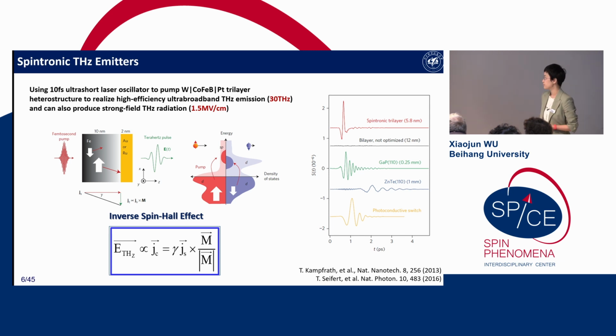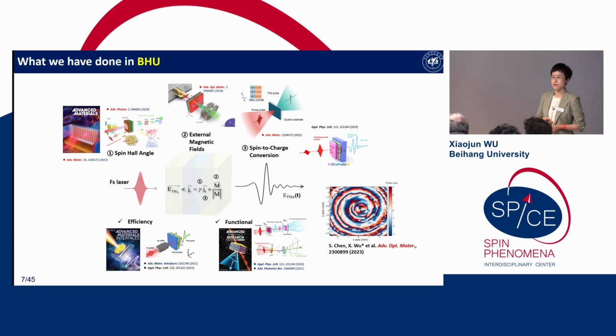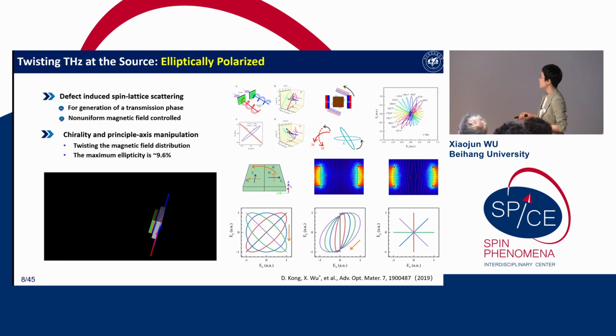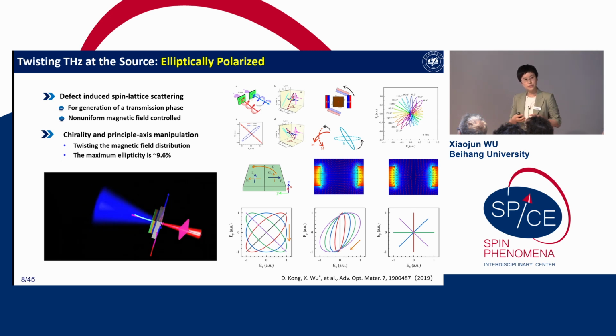What we have done at Beihang University these years is, based on this spin-to-charge conversion formula, we change the non-magnetic metal to some topological insulators, and we try to optimize the spin Hall angle, manipulate the external magnetic fields, and enhance the spin-to-charge conversion efficiency. The first goal is to increase the terahertz emission efficiency. The second is whether we can shape the terahertz at the source to fabricate functional terahertz devices at the emitter. For example, at the beginning, we used a non-uniform external magnetic field, and we produced an elliptically polarized terahertz beam directly at the Spintronic terahertz emitter.